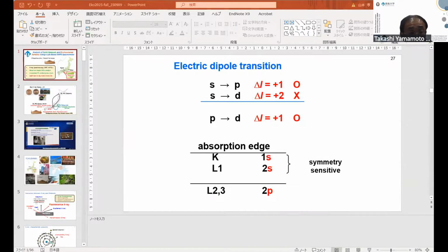The p electron can transition to the d orbitals. In these regions, the K-edge and L1-edge are transitions of s electrons, and this is symmetry sensitive. But for L2 and L3 edges, these are 2p1/2 or 2p3/2 electrons, and the transition to the d orbitals is possible. The outer shell is d orbitals, so maybe a large peak exists. This is not sensitive to the coordination environment.